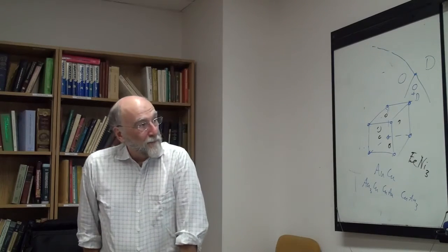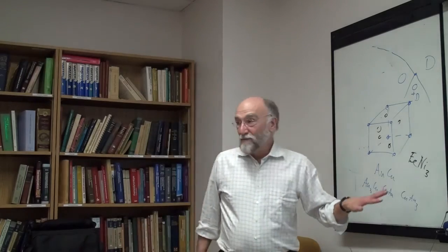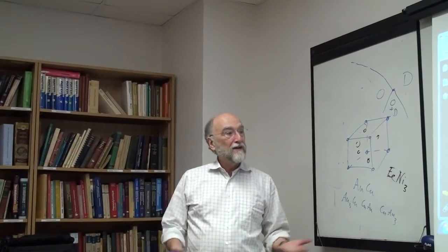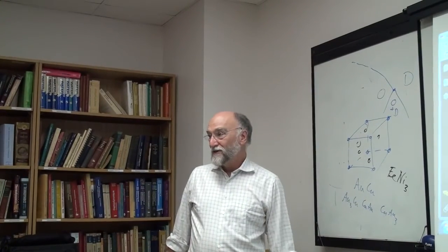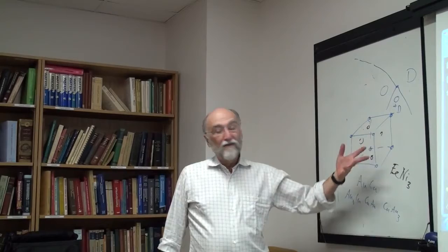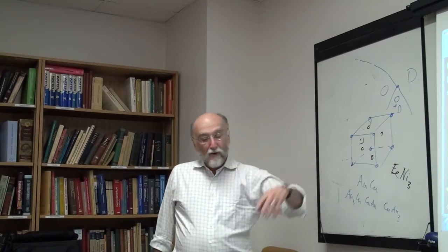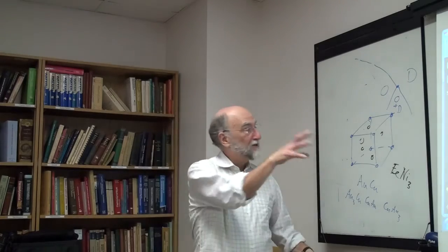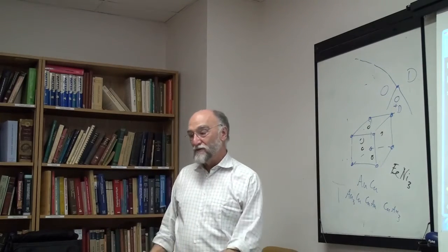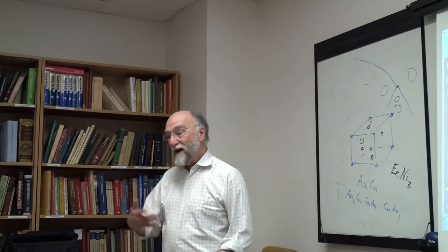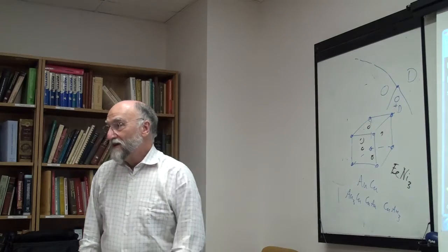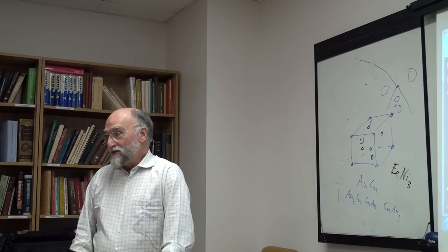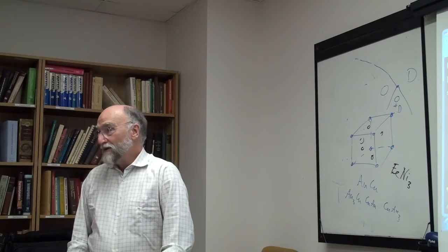But anyway, the point is, for any practical aspect, even if it is all right, it's got so many terms that for any practical calculations, you couldn't do it. You end up with a huge number of end members, because remember, in the quadruplet model, every quadruplet is an end member. If you have an octahedral model and tetrahedra, then you've got like 60 end members for a binary system or something. And imagine trying to predict ternary and quaternary phase diagrams in a database when you'd have hundreds and thousands of end members. It just becomes mathematically intractable.